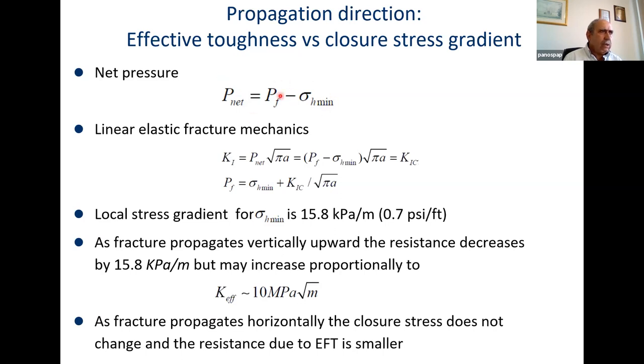Then I try to do some comparisons here. So I started with the definition of the net pressure, which is the pressure in the fluid minus the closure stress. And for linear elastic fracture mechanics, the stress intensity factor is the net pressure times the square root of pi times the half length of the fracture. We can write it like that by replacing the net pressure, and the fracture will propagate when we reach the fracture toughness. So then I can solve for the pressure in the fracture, which is the closure stress plus the toughness divided by the square root of pi times half of the fracture length. So this is the equation now.